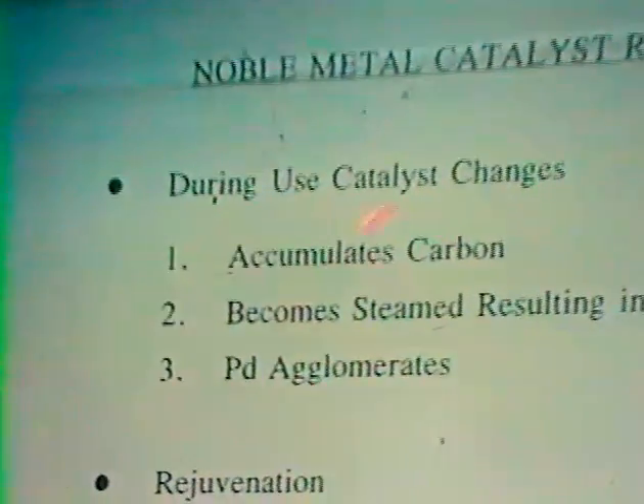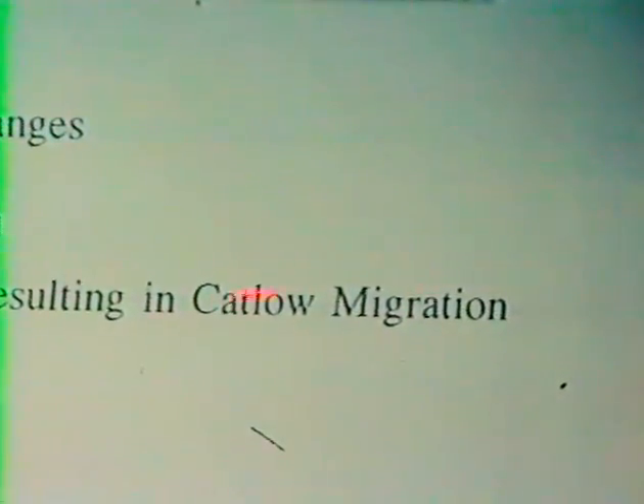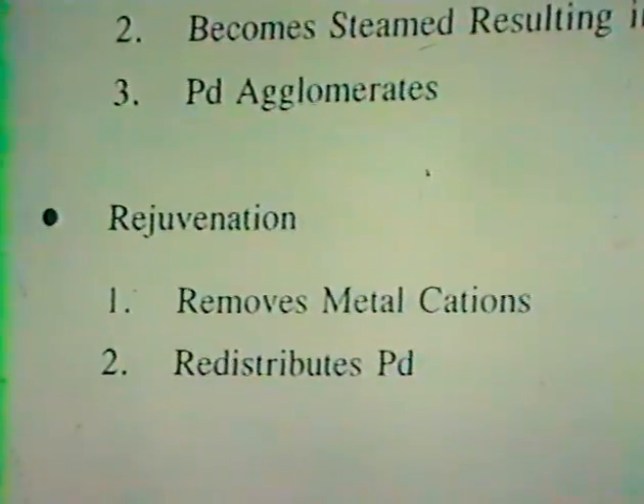As we mentioned previously, during use, these catalysts will deactivate due to carbon deposition. They also become steamed. They're steamed, which results in cation migration and also palladium agglomeration. Now we can restore the activity of these catalysts by taking out the metal cations and redistributing the palladium. We'll show that on the next slide.